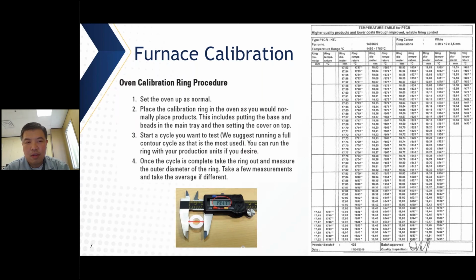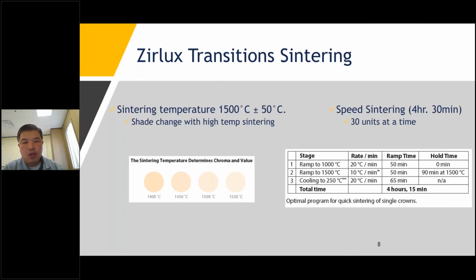to fire them on. Okay, so if you know that your oven is dirty and hasn't been cleaned forever and hasn't been calibrated, this is a good way to go through your cycle to make sure that your oven is back to optimal condition before you work on your zirconia. Okay, so this is the range of zirconia you can actually see down here. Even though it says that it's supposed to be fired at 1500 degrees, the temperature changes will actually make your zirconia have a different shade.